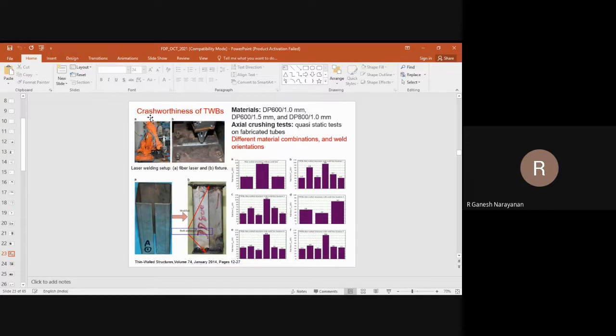So if you're going to make such components with tailor welded blanks, what's going to happen? That's what it's going to tell you. They have made square tubes out of tailor welded sheets, and they are going to actually crush them, either by quasi-static test or by dynamic testing. Okay, and they have used DP600 with different thickness combinations, you can see, and an axial crushing test was performed, and they have also done different orientations.